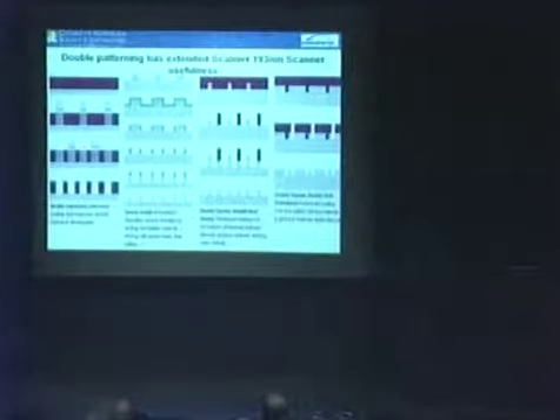So we take another approach. Another approach is we put these patterns down, then we deposit metal, we strip that metal off the top, and we get these little spacers. We can get rid of the resist, then we get these spacers, very small. We can print these patterns, and all of a sudden, look at that. We can etch those into the substrate, and we have the pattern that we were trying to print in the substrate. And we get some good etch resistance from these things because they're made out of metal or something like that. Hard mask, we call it, very hard material, right? And it gives us what we wanted, the 2 lines close together in the final pattern. So that's one approach. Problem? These are very expensive processes. And there's extra processes. Extra processes mean more money. Every time it goes through a process, costs us money.